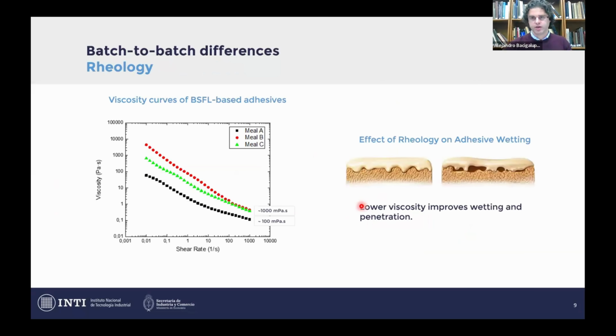So our next test was rheology. Protein adhesives act as non-Newtonian materials, and viscosity has a very important role in wetting of the wood surface. If you have an adhesive with low viscosity, you will have a uniform and good wetting of the wood. If you have a sample with high viscosity, like B and C, you will have poor wetting properties. So we believe that for sample C, one factor that is affecting the mechanical properties is the rheology of the adhesives.